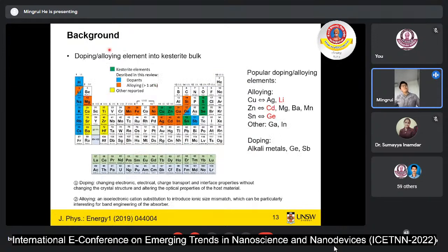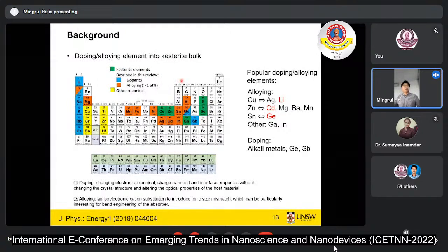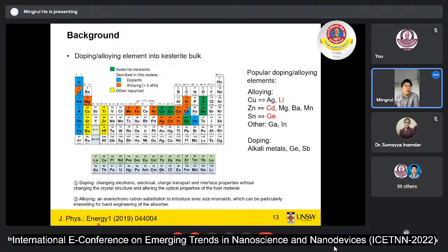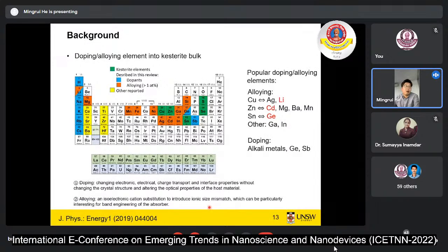So here is the background for my method: how I am going to change the defects in the CZTS bulk material. One way to change the defects is doping or alloying new elements into the kesterite materials. If we dope, we can easily change some of the properties. And if we alloy something, we can change some mismatch in the lattice, which will also reduce the formation energy of some of the defects.